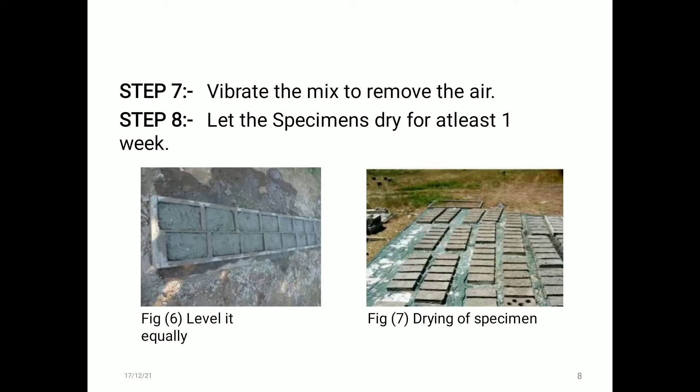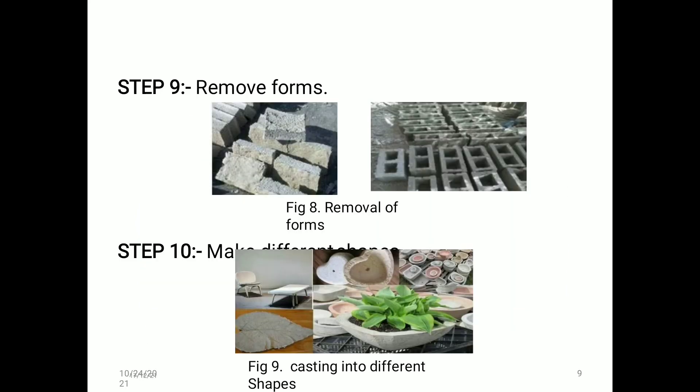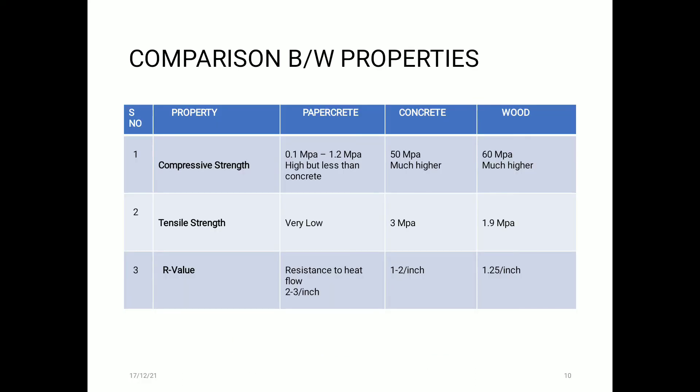In step seven, vibrate the mix to remove the air. In step eight, let the specimens dry for at least one week. In step nine, remove the forms. And in step ten, make different shapes.